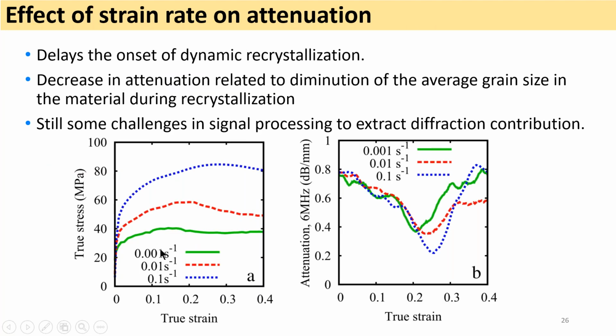Of course, I've done several experiments in which the strain rate this time is changed. In metallurgy, if we decrease the strain rate, the dynamic recrystallization will occur at lower strain. That's what we see in the true stress strain curve. For the green line, which is a very low strain rate, the dynamic recrystallization starts at about 0.15 true strain. It only occurs above 0.2 or maybe 0.3 strain in the case where the strain rate was 0.1 second to the minus 1. And here on the right hand side, you can see that indeed we see this decrease and this minimum occurring slightly later in the case of the attenuation signal.